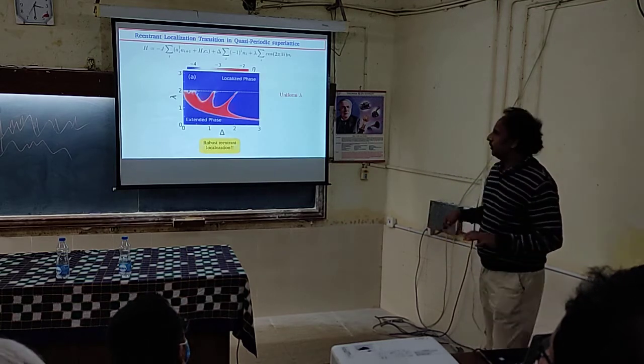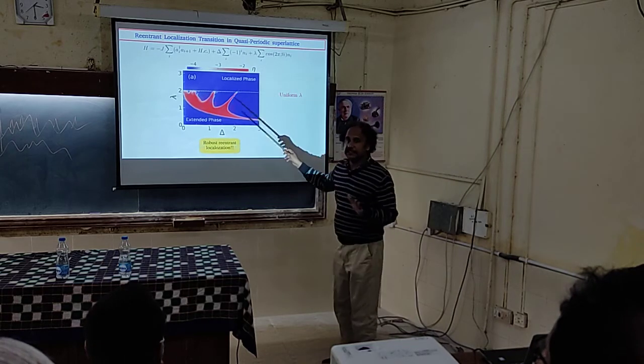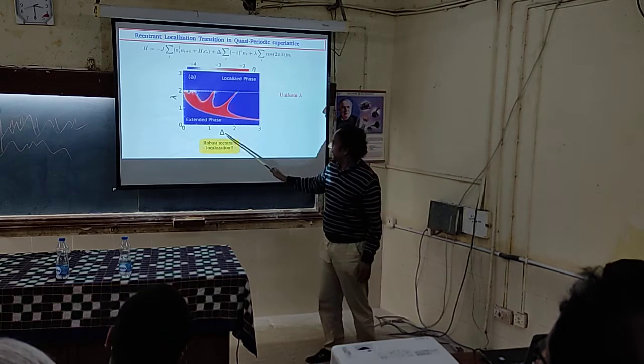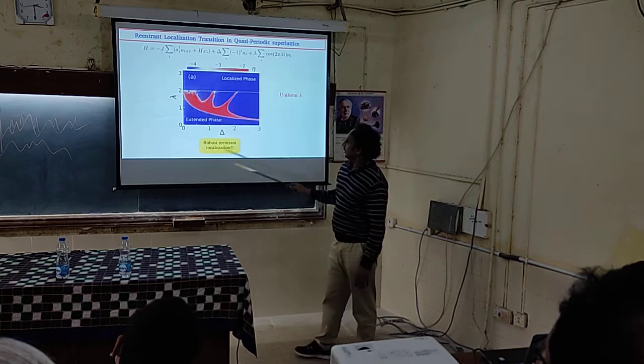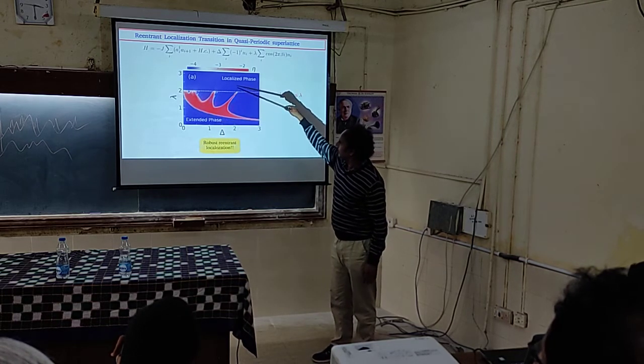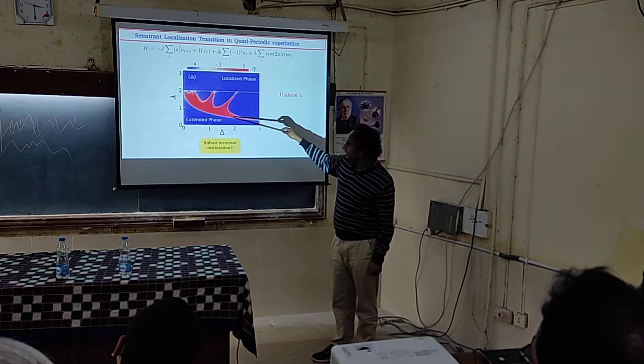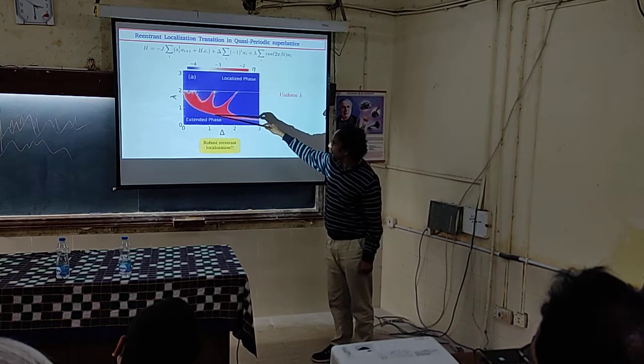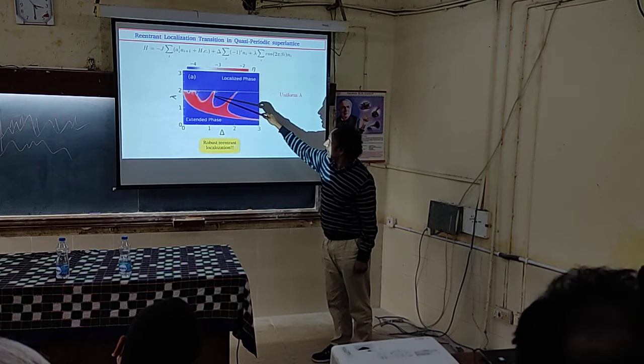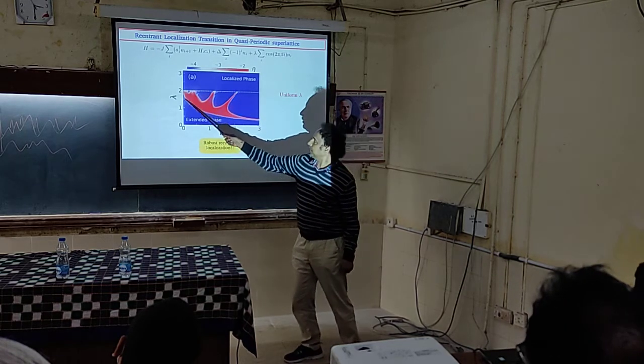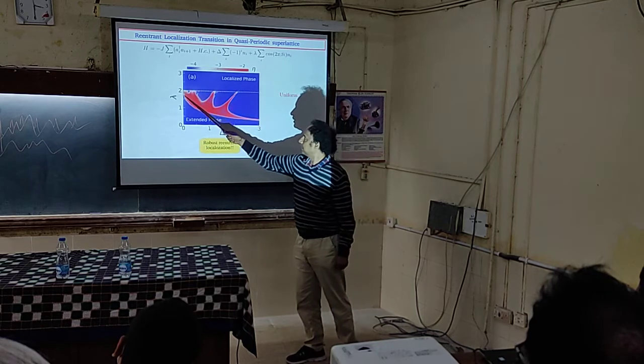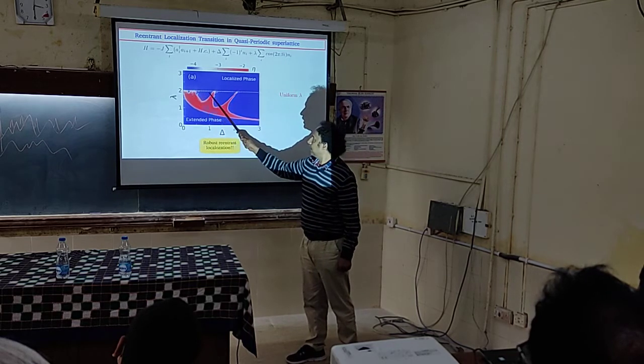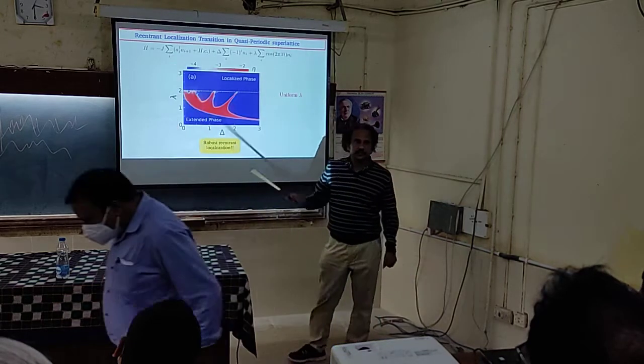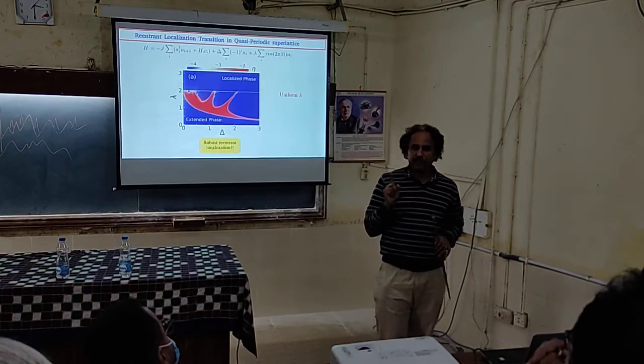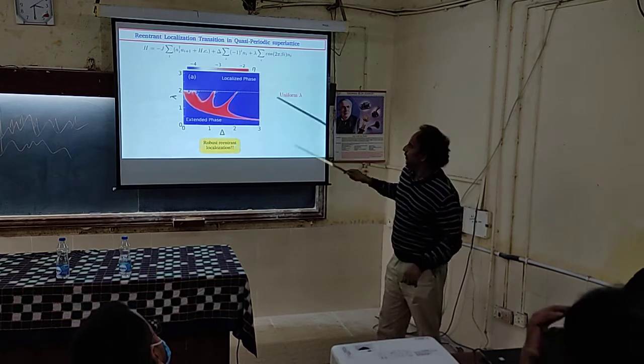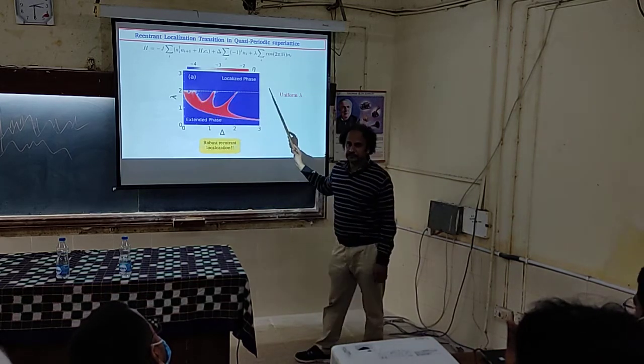Now you see. Look at the phase diagram. This is even richer. So if you look at the phase diagram, this is your delta, this is lambda. Now if you go like this, you certainly hit two different critical regions. One critical region, another critical region. So you go from here, extended, critical, localized, critical, and so on. But if you go from here, look here. Extended, critical, localized, critical, localized, critical. It's a series of localization transitions, not only one localization, relocalization transition. It's a series of re-entrant localization transitions.